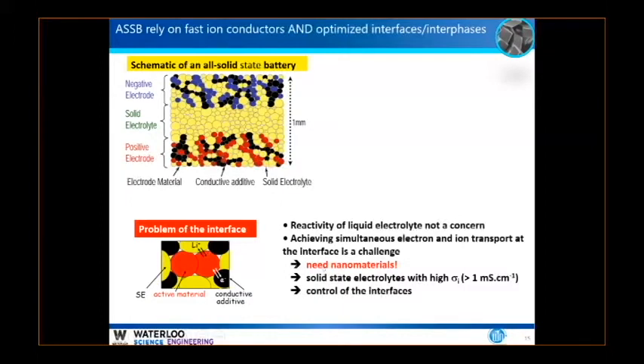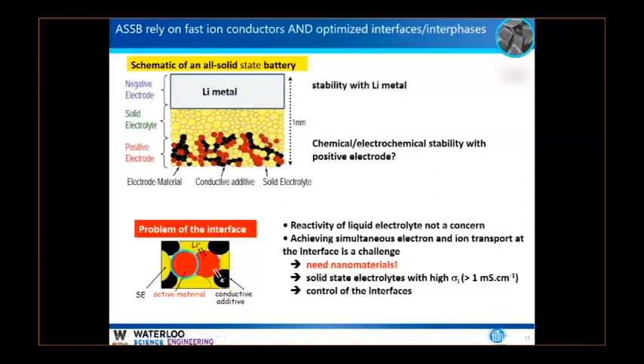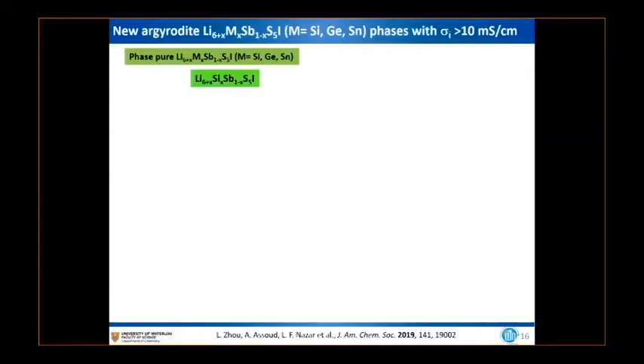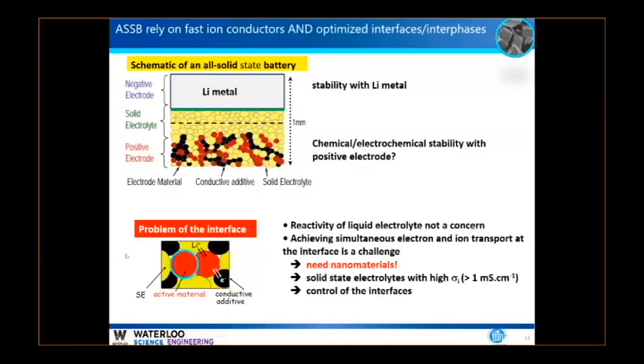And this is where we desperately need nanomaterials. And we need solid electrolytes, these yellow things here, with high ionic conductivity, where a benchmark is typically about 1 millisiemens per centimeter, which is a metric for conductivity. And we need to control the interfaces. So one of those interfaces is especially the stability of these electrolytes with the active cathode material, and I won't have time to talk about the stability at the other side. So one of the things that we have to do actually is create coatings around the cathode material in order to inhibit that reactivity, and I'll be discussing that briefly.